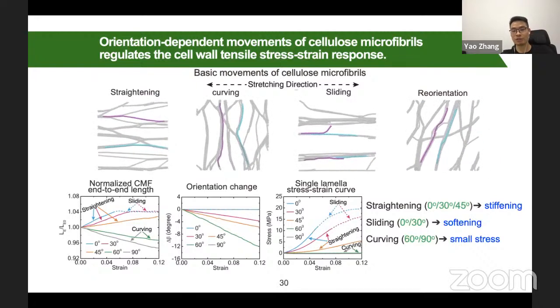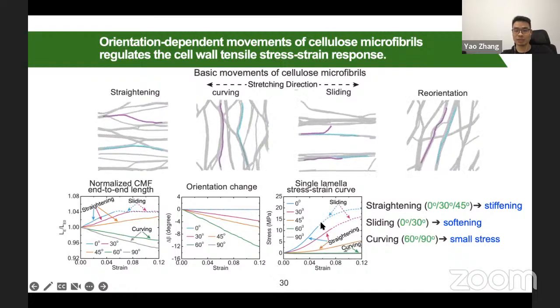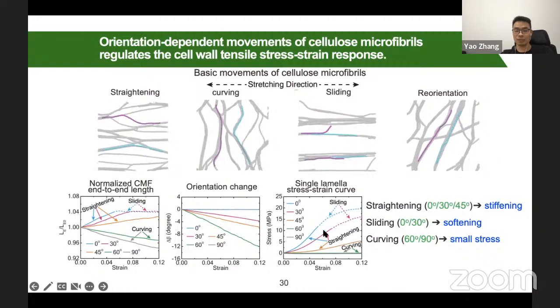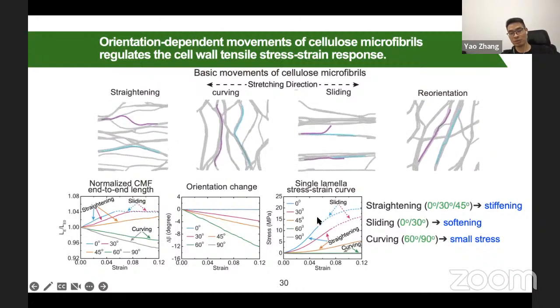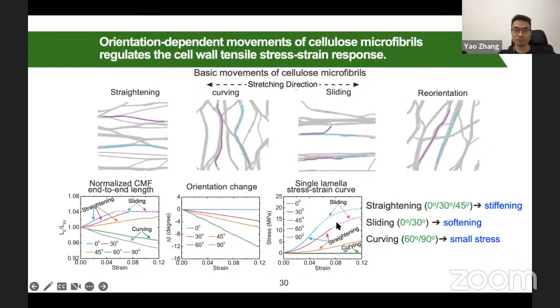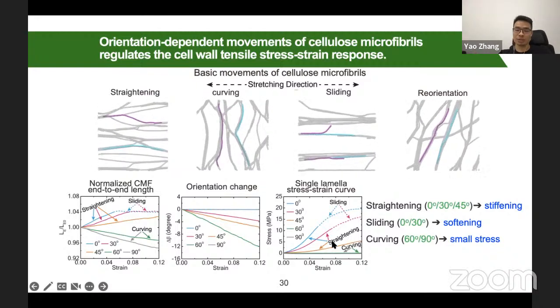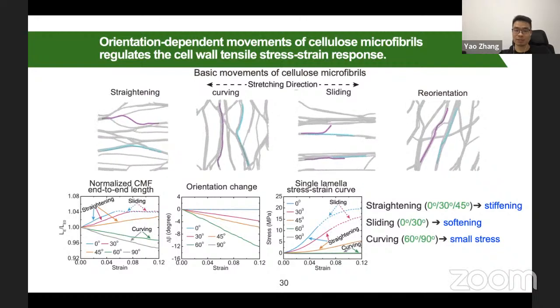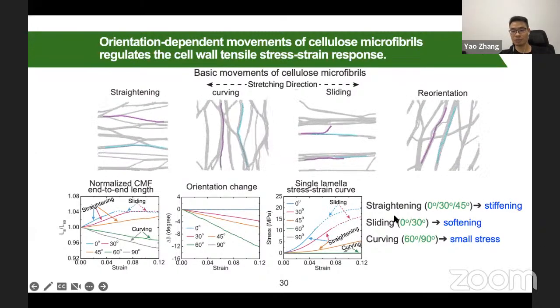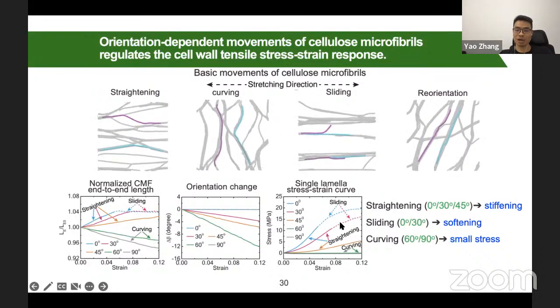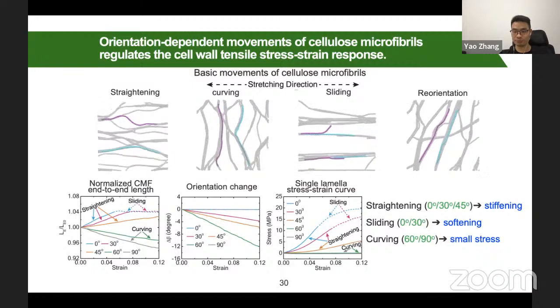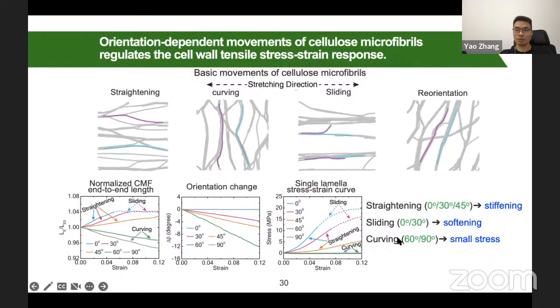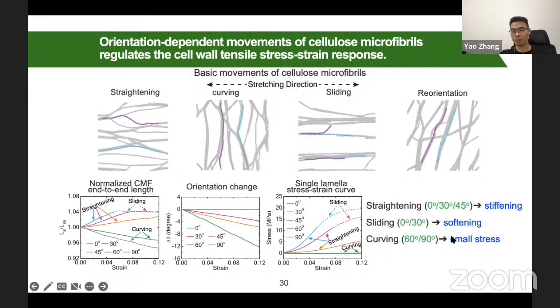And also we try to link the stress-strain curve with the movement of these cellulose fibers. Here it shows the stress-strain curve of different lamellae, which have different cellulose orientations. So basically we conclude that when the cellulose has a movement of straightening, the modulus of the lamella will increase, which is the stiffening region. When sliding happens, which is marked by the dashed line, softening will happen, and the modulus of the lamella will decrease. Also, in some cases, if your cellulose fiber orientation is very large, the lamella will not carry much stress.